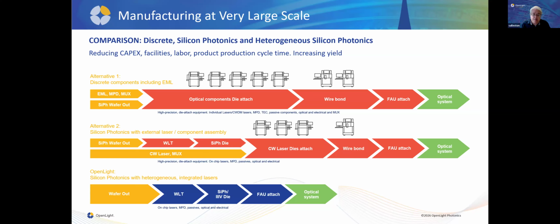Silicon photonics actually takes a lot of this pain out. You're now creating a lot of components in a single die. You can test it at wafer level and then dice it out, but you still have to attach the components that you cannot build. So you're not really saving as much as you might think. The real advantage of heterogeneous integration is that we're taking those die attach stages away, so that 90% of the manufacturing process can be like a standard, almost SMT type process. And then the last step, the FAU attach, is the only thing you really need to do that a typical contract manufacturer can't handle today. So it's really set up for scaling.